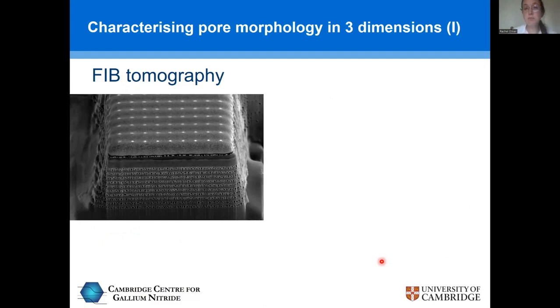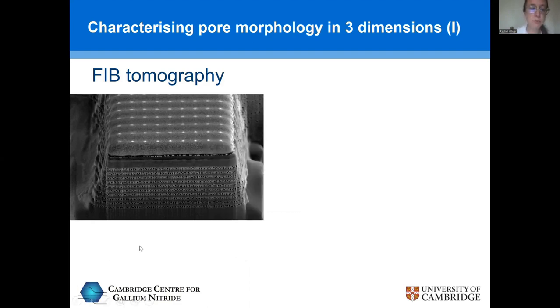Just to show you, well, do we really have aligned pores? I'm going to show you another microscopy technique. I'm into microscopy. I suspect this is unusual for this audience. Another microscopy technique that we can use to show that we have these aligned pores. This is again in the focused ion beam microscope, and we've created a sort of big fat mesa out of our DBR here with these aligned pores. And what we're going to do is take a SEM image and then use the ion beam to slice off some of the material, a bit like slicing a bar cake or a loaf cake.